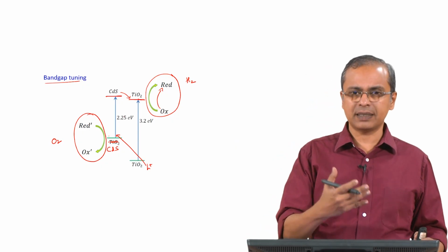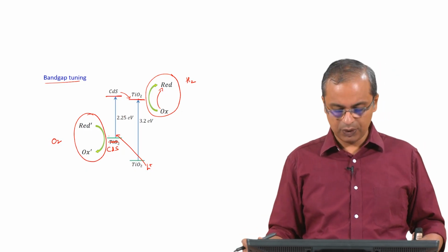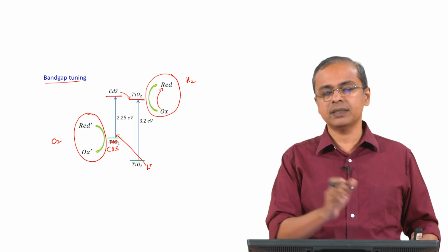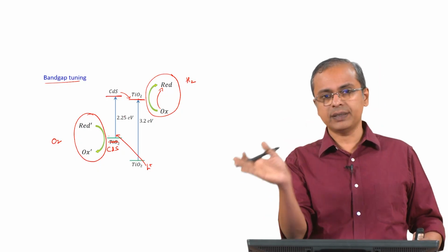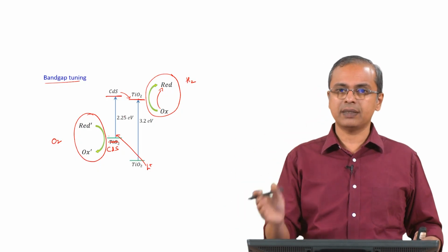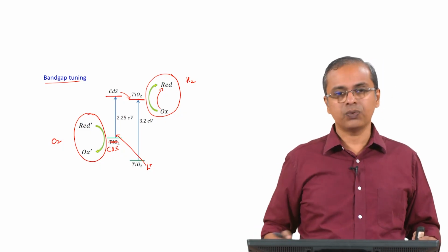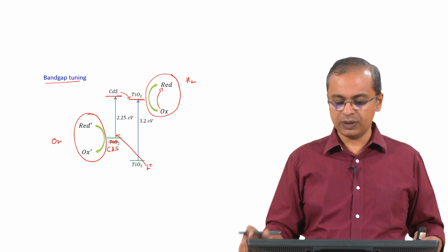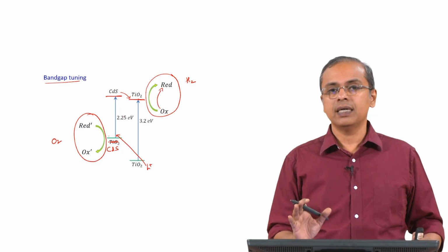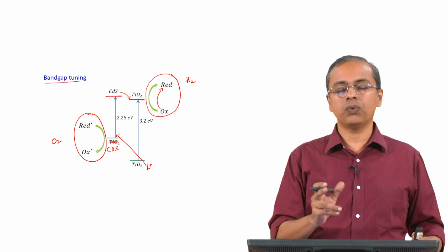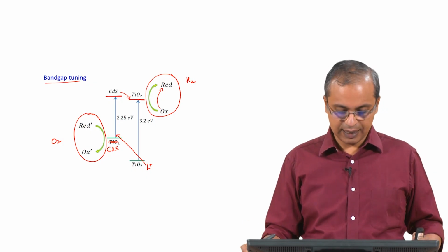It is sort of like a p-n junction, although you are not necessarily looking at it as more than a junction between two materials, and you may not have doped it in any way. But you are creating a situation where electrons will preferentially stay on one material, and the holes will preferentially stay on the other material. Therefore, you generate oxygen at a slightly different location than hydrogen, and more specifically the electron holes have less of a tendency to recombine, because you have now given them an opportunity to stabilize themselves at different locations.